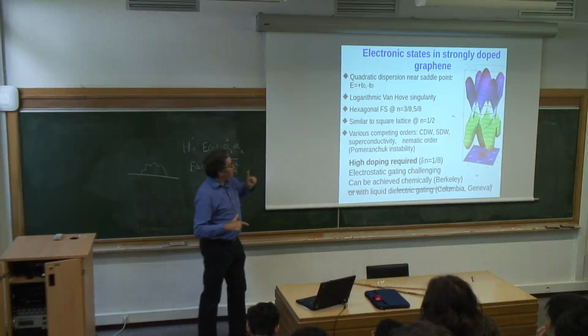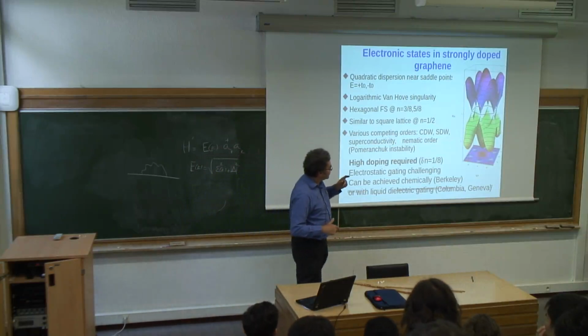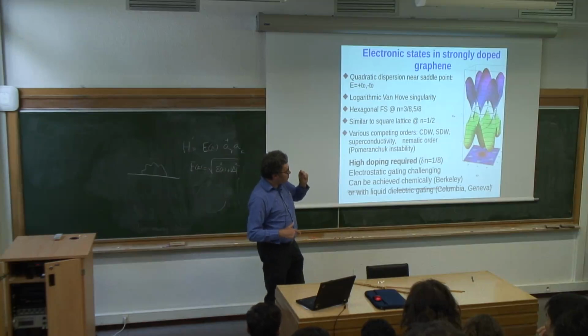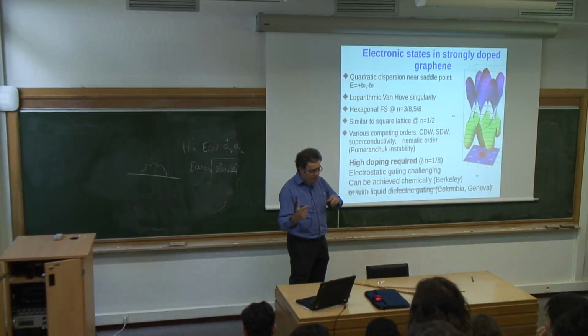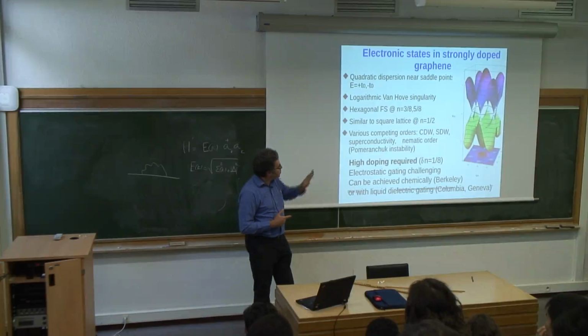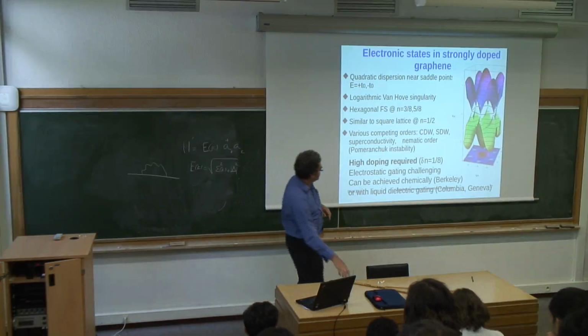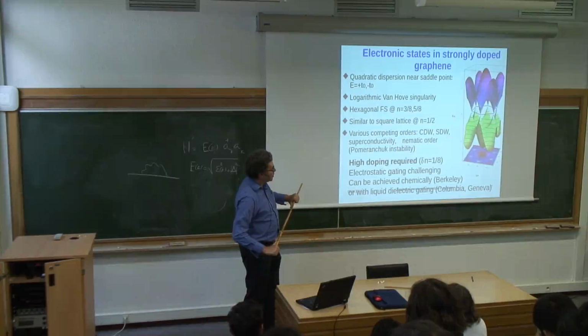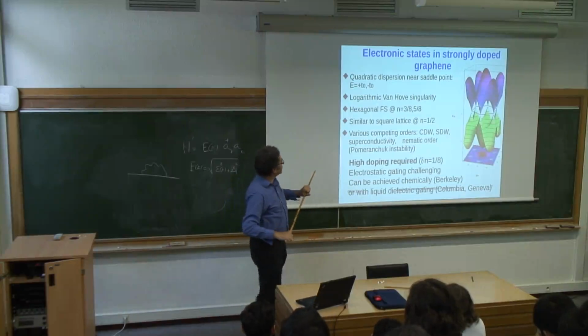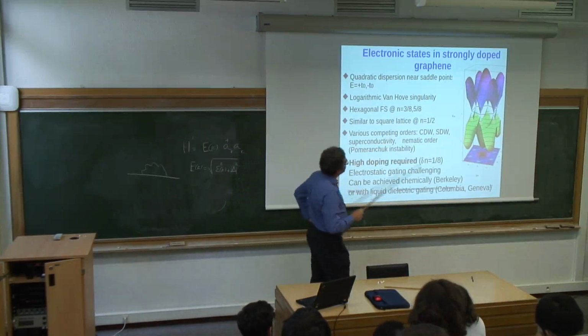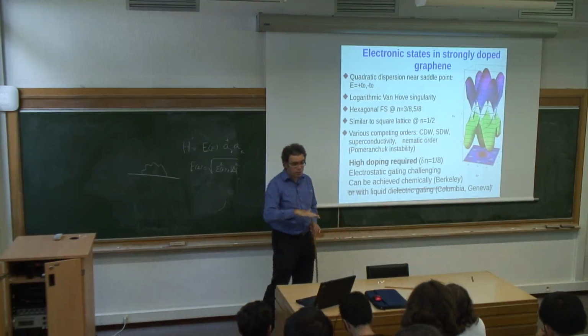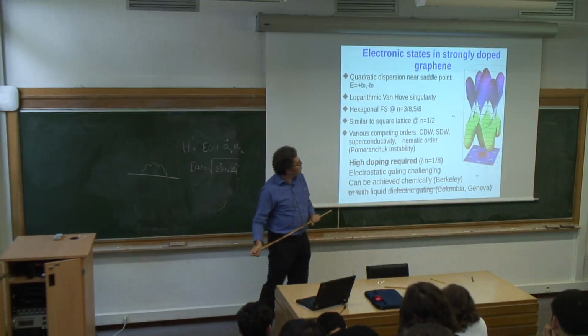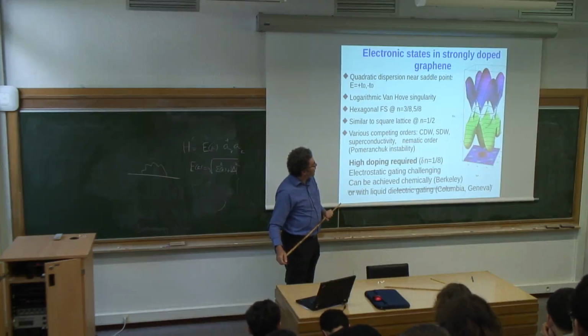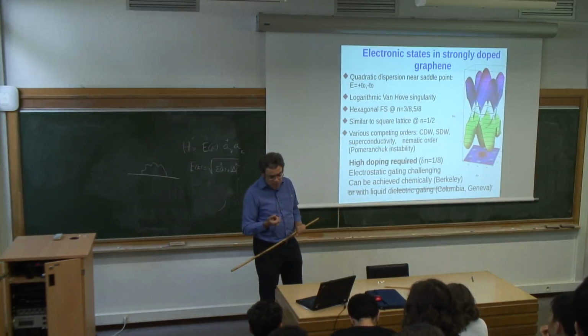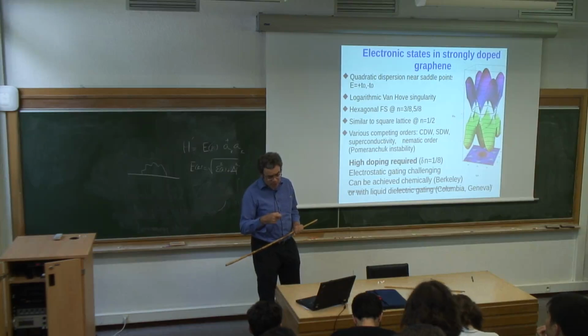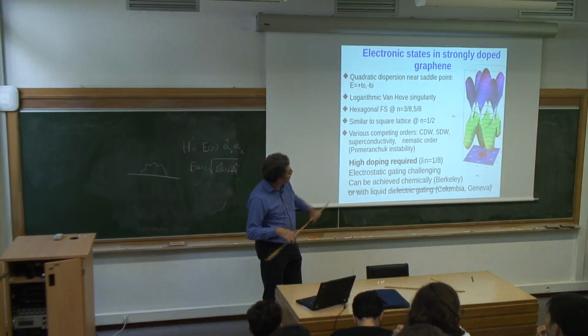And so if you try to work along these lines, trying to introduce density of states as an enhancement of superconductivity, then you find that other competing effects, spin density wave, charge density wave, are also enhanced, and so that's the issue here: how superconductivity competes with other orders. And so what we have to stop, but basically one can do analysis for graphene for pure Coulomb interaction, no phonons, internal, external, Coulomb interaction only, and then what you find is that because of having several valleys, in this case, Coulomb interactions lead to superconductivity, which wins over other orders, and you get